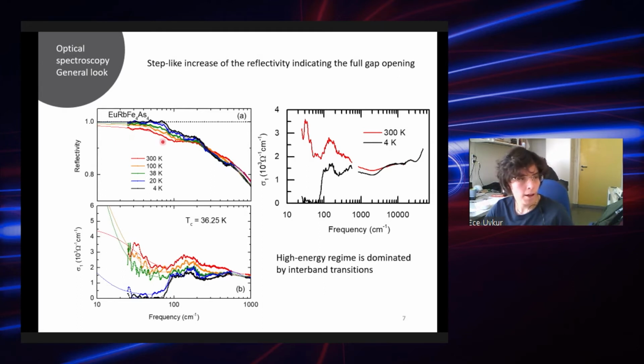And when you pass below 38 Kelvin to the superconducting state, the reflectivity shows a step-like increase that almost reaches unity. When you convert this reflectivity to the optical conductivity, what you see is some sort of Drude-like increase in the low energy range. At room temperature, maybe it's a bit more clear. And once the system goes into the superconducting state, the conductivity drops to zero. So all the Cooper pairs condense into the delta function here, and then you could observe this superconducting gap.